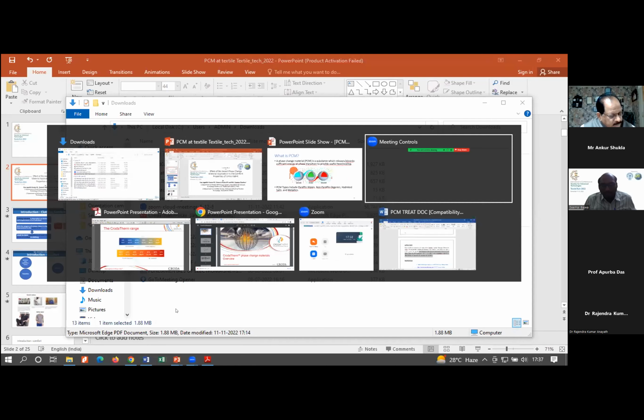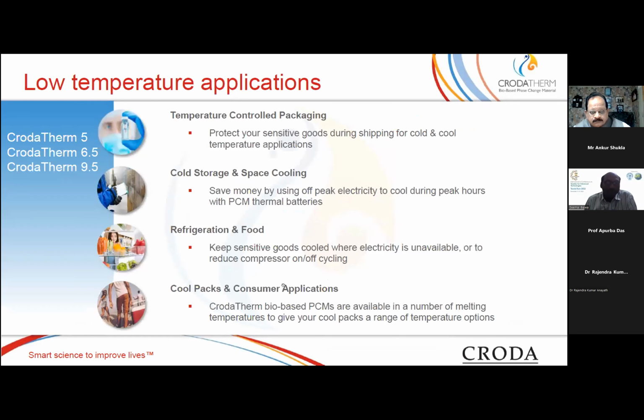Let me show you one of the materials which we have selected, which is made from protein. It has a range of 5 degrees to 74 degrees centigrade: 5 degrees, 6.5, 9.5, 15, 19, 21. These are the cold temperature, ambient temperature and high temperature ranges, depending on where it will be used. For 5 degrees, 6.5 degrees and 9.5 degrees, the phase changing materials are used to protect sensitive goods during long shipping, in cold and cool temperature combinations. Slowly it releases the saved temperature.